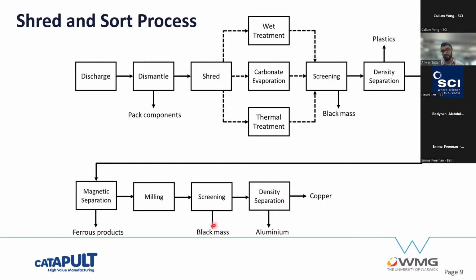Now, this black mass contains about 90% of the value in the cells. And most of that value is in the lithium, the nickel, and the cobalt. And then there's a bit more value in the copper as well. But those four elements contain, I would say, 95+% of the value in lithium-ion batteries or end-of-life lithium-ion batteries.